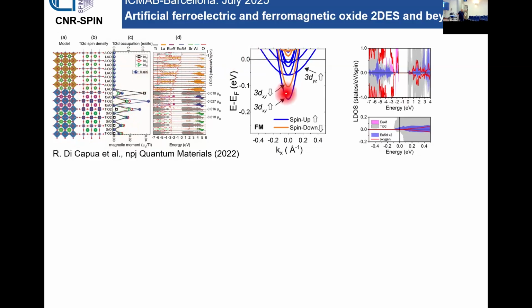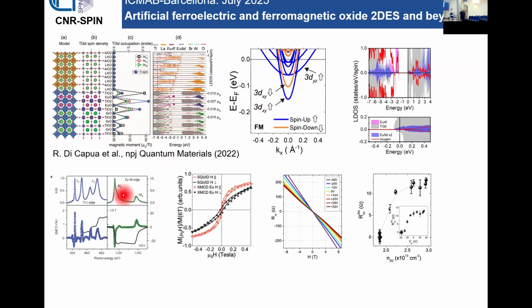The bands are completely split, spin up and spin down band, so it's essentially a spin-polarized 2DEG. Indeed, it shows both a titanium XMCD signal, so this is a measurement of magnetic moment, and a europium XMCD signal. The system is essentially a ferromagnet with in-plane easy axis. And the effect of these magnetic properties is reflected in the anomalous Hall effect. This Hall effect data is showing an anomalous component, which can be tuned by the gate voltage.